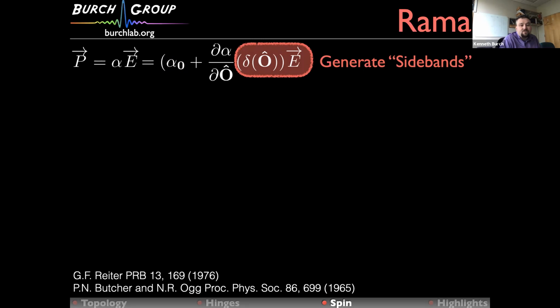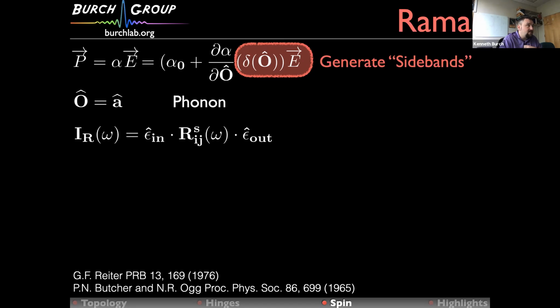And this is actually how Raman was discussed in the 60s, essentially as a noise measurement: you're really looking at noise coming off of your reflected light. To ground things a little, it's very natural to have the susceptibility coupled directly to the lattice displacement, and therefore the fluctuations you're seeing are just phonons. What's nice about this way of thinking is that, because it's the derivative of alpha with respect to the operator, the Raman response is a tensor, since you're coupled to both the incoming and outgoing polarizations of the light. It also shows you why it can be challenging, because even in the best cases, it's something like 1 in 10 to the 8 photons that are Raman shifted. And for magnetic responses, it's usually far worse than that.